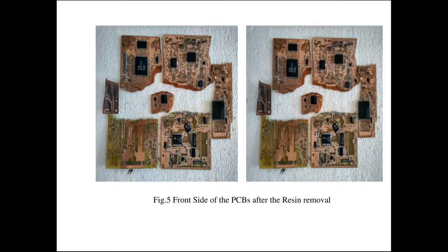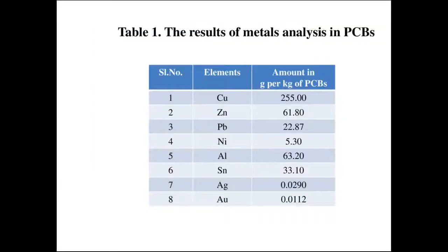We have dipped the broken PCBs into the NaOH solution. Due to the high thermal evolution from the NaOH solution, the resin has been removed from that. Why have we removed the resin? It is a very inhibiting compound for bacterial growth to recover the various metals.